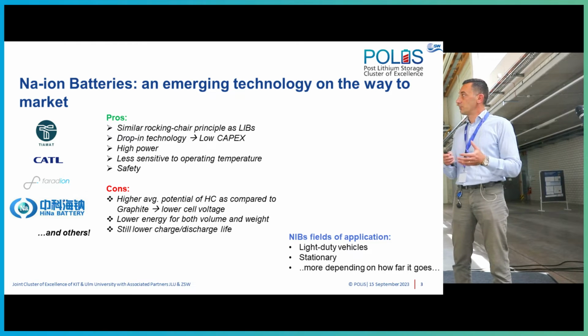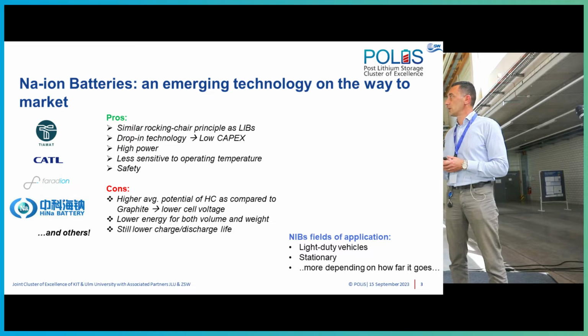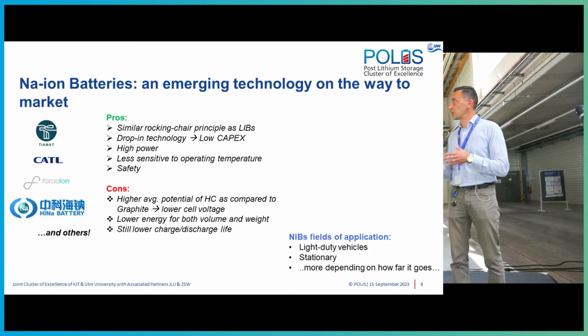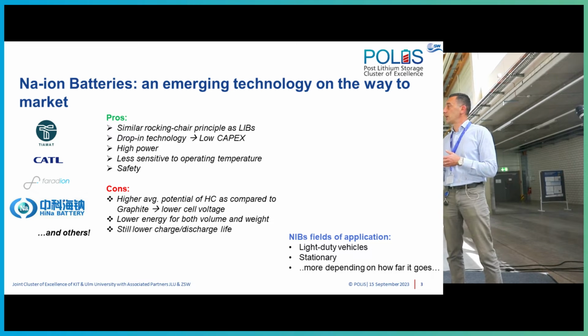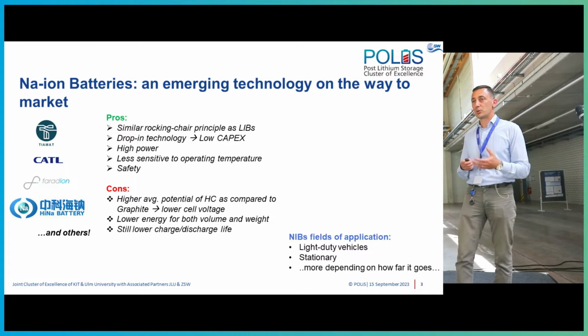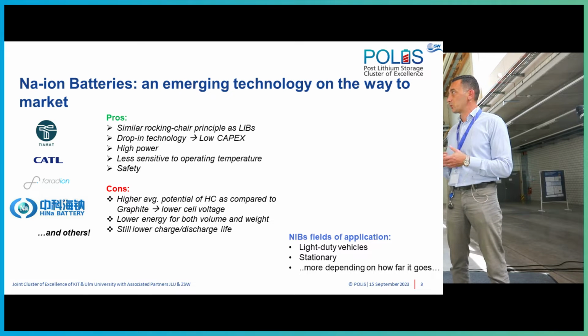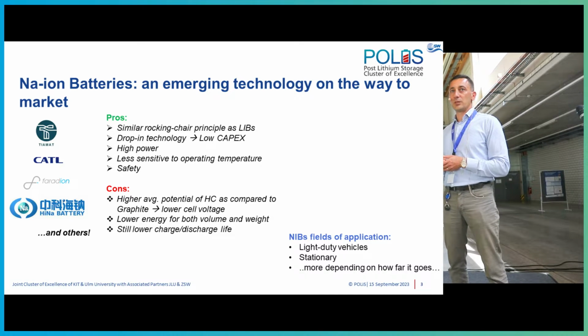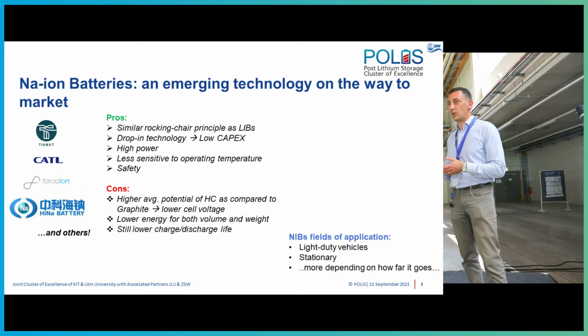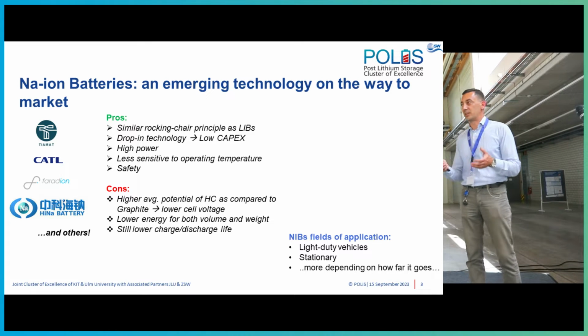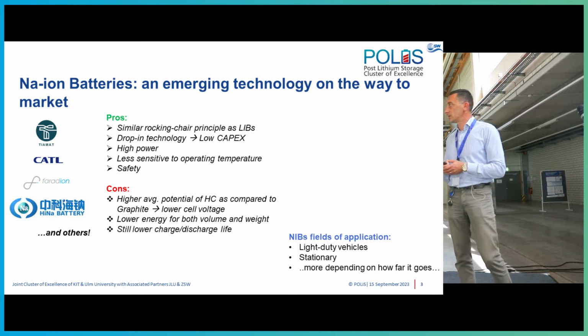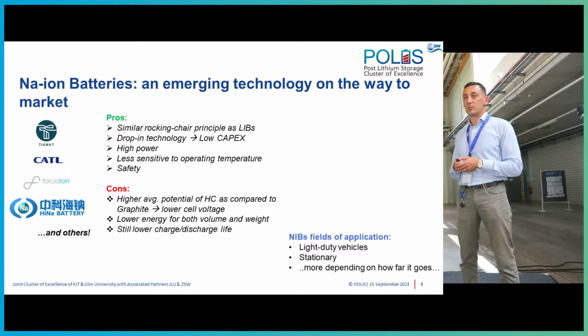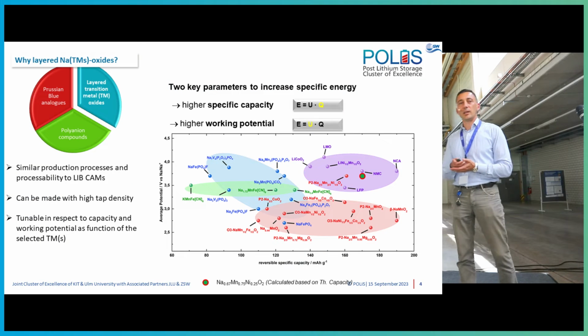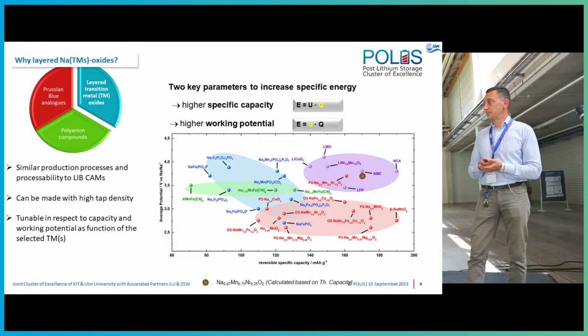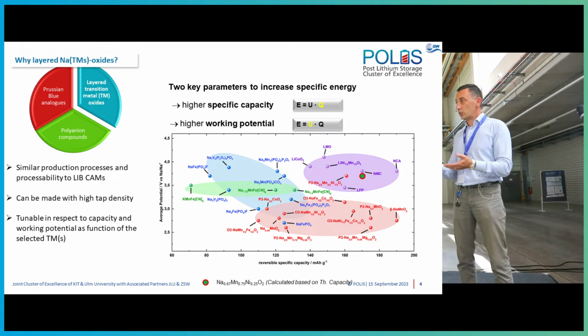Then again, the layered transition metal oxides have an edge with respect to the others, probably because they share similar production processes and processability with lithium-ion battery cathode active materials. Let's just think of cobalt oxide, nickel manganese cobalt oxide, all the layered oxides. They can be made with a high tap density. Tap density will directly impact the energy density that you are actually able to pack in your cell.